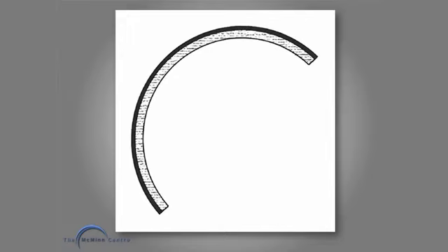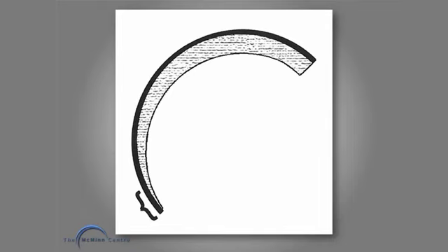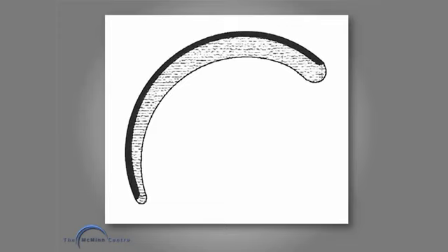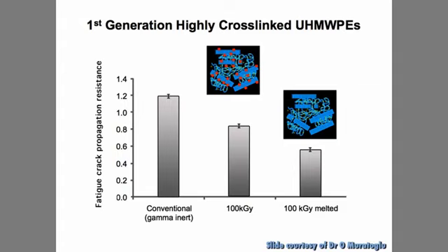And that's not enough. You can help matters a little bit by displacing the inner center outwards and downwards. And that will increase the thickness of polyethylene in the superior wear zone area. But of course, it reduces down to 0 the polyethylene in the inferior aspect of the cup. Now, there are many cup designs from the past with an inferior cutout, and if you do an inferior cutout on this design, then you can get a reasonable thickness of polyethylene all around with a good thickness of polyethylene in the wear zone.